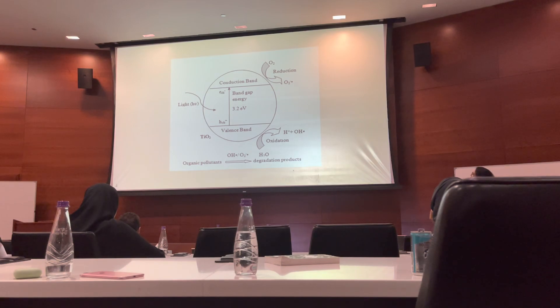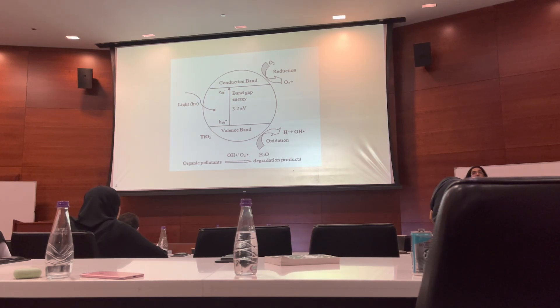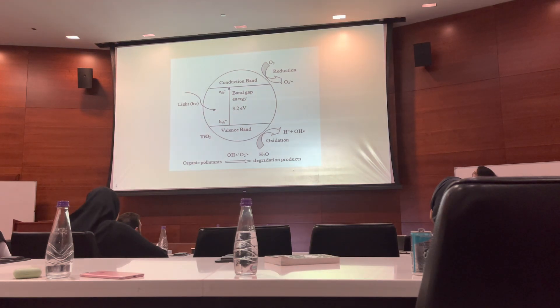Once that electron is excited, it reduces an oxygen molecule to an oxygen radical. The remaining hole — essentially the absence of an electron — can produce hydroxyl radicals. These hydroxyl radicals are the same thing used in cleaning products that clean your clothes or tissues. What we're attempting to do is degrade these dye molecules using this extremely environmentally safe and cost-effective process.